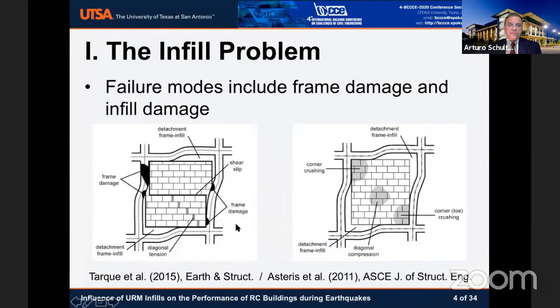Some are associated with the masonry itself. And so if you have weak mortar and strong units, you may get sliding along horizontal joints. This is especially pronounced when the length of the infill panel is much larger than the height. You can get cracking along the diagonals, either in the form of a stair-stepped configuration if the units are strong, or cracks that go through the units if they're not strong.